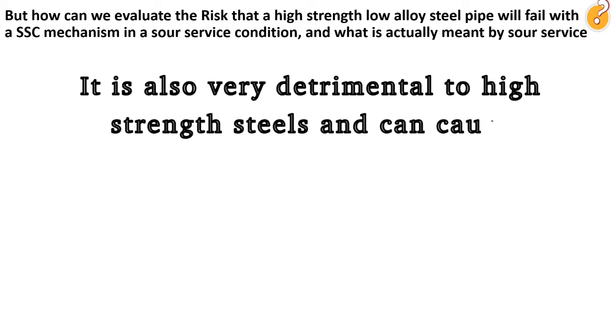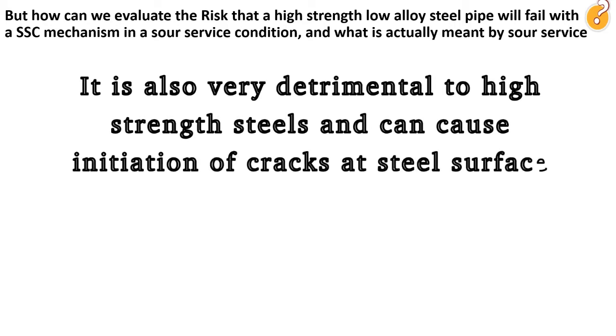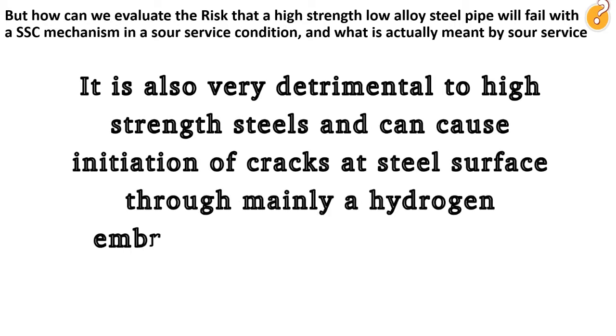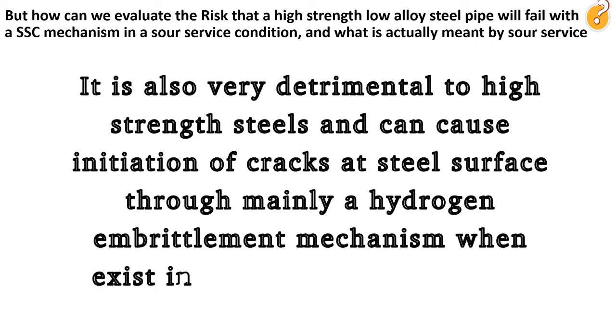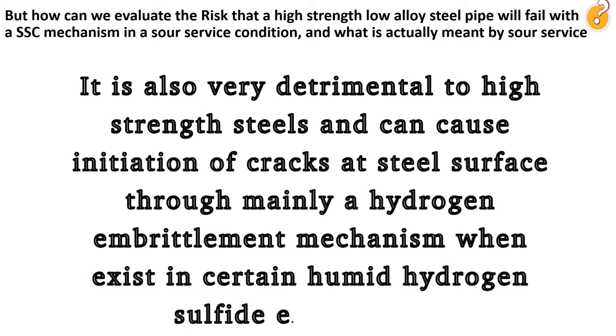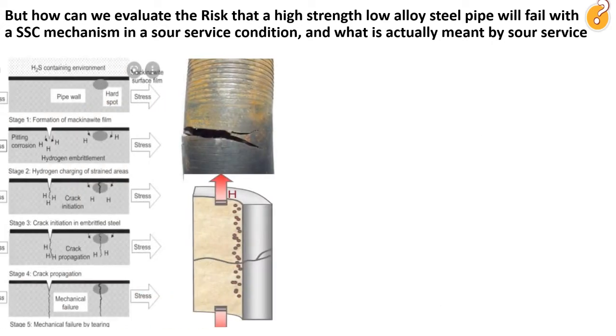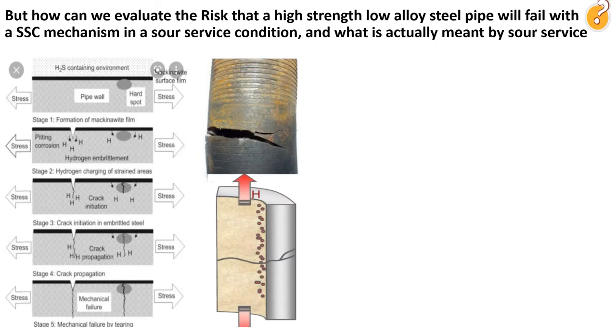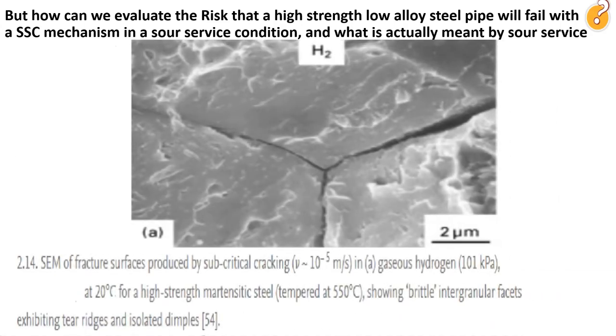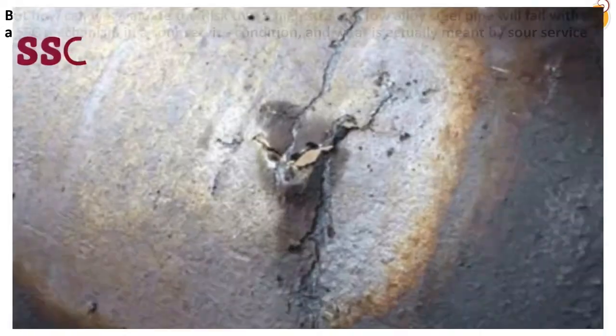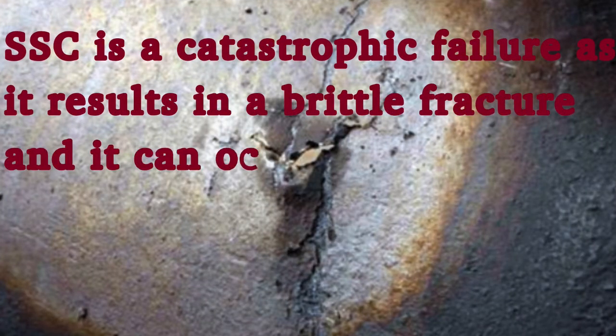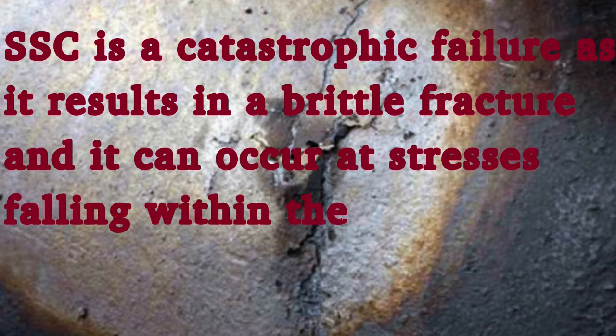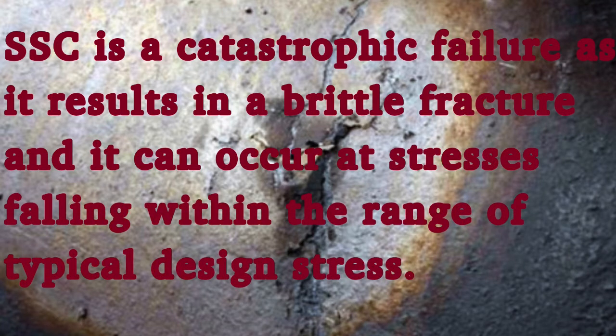H2S is also very detrimental to high-strength steels and can cause initiation of cracks at the steel surface, mainly through a hydrogen embrittlement mechanism, when it exists in certain humid hydrogen sulfide environments, especially if combined with certain stress loads. This is why it is called sulfide stress cracking. SSC is a catastrophic failure as it results in a brittle fracture, and it can occur at stresses falling within the range of typical design stress.